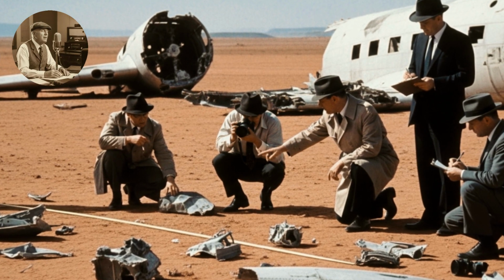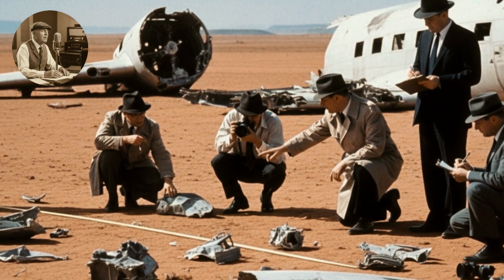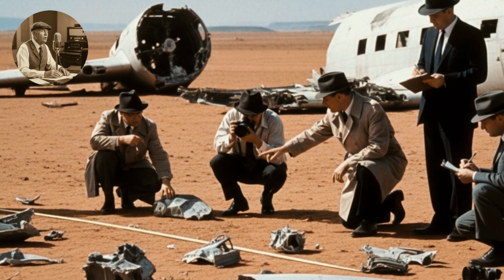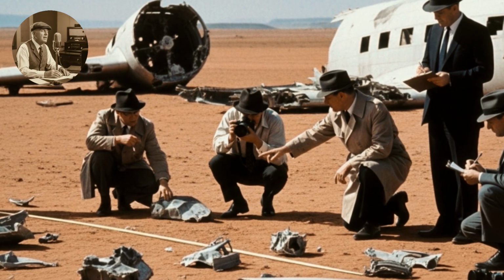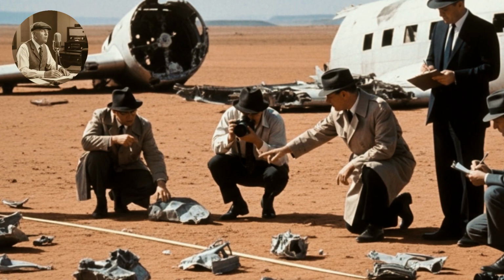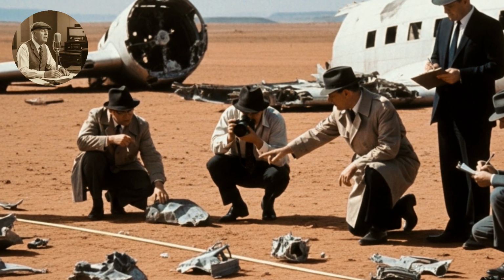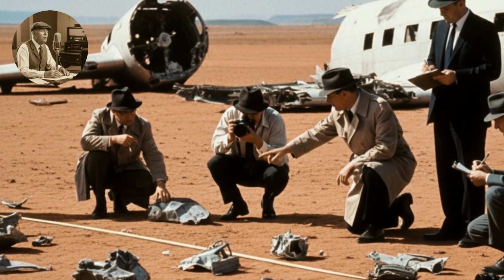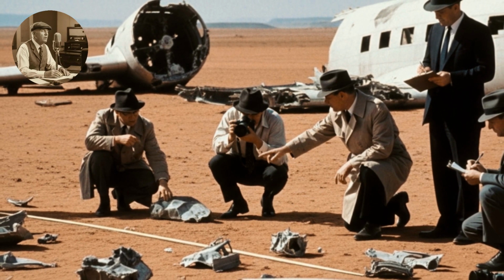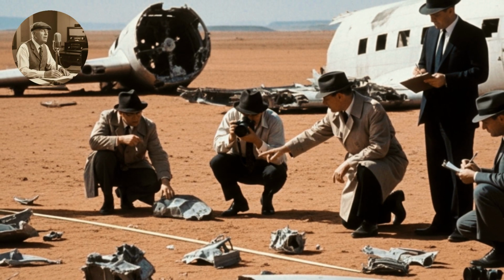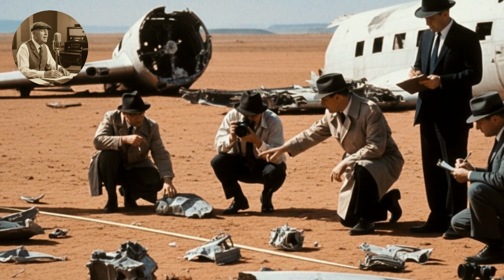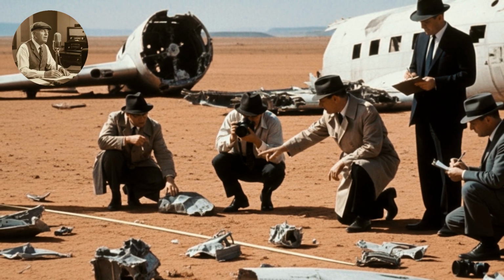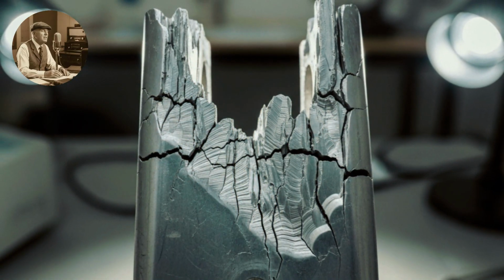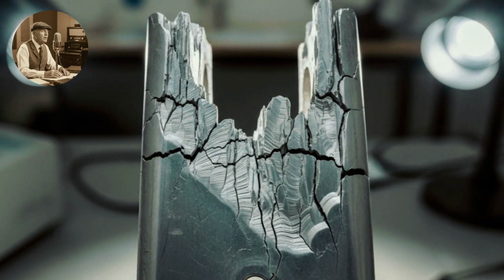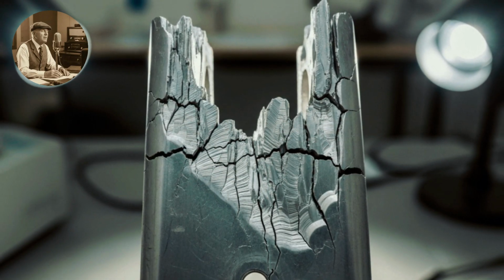In structural failure investigations, the surface of a fracture often tells a detailed story about how the break occurred. Fatigue cracks produce distinctive patterns that differ from sudden overload fractures. When engineers examined the broken spar components from the right wing, they observed exactly such patterns. The fracture surface revealed a large fatigue crack that had propagated gradually through the metal. Using microscopic analysis, investigators determined that the crack had grown across approximately 85% of the spar's cross-section before the final fracture occurred. This meant that only a small portion of intact metal had been supporting the load during the aircraft's final flights.